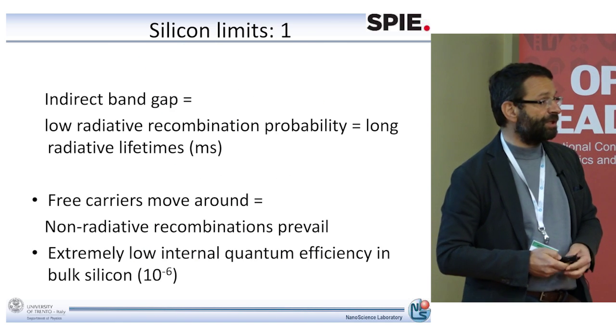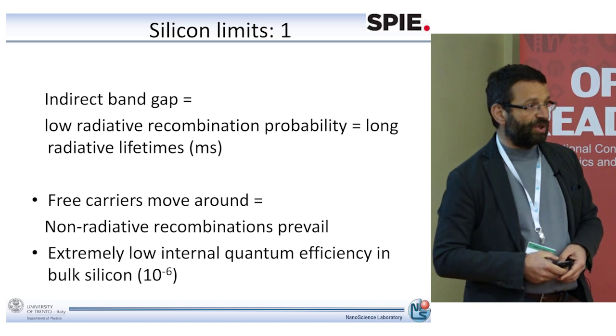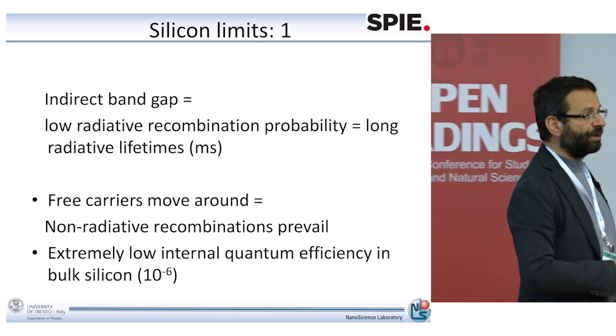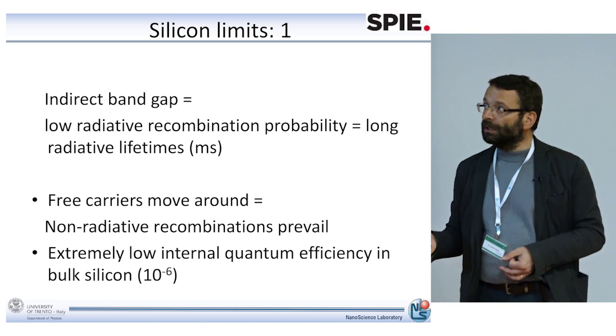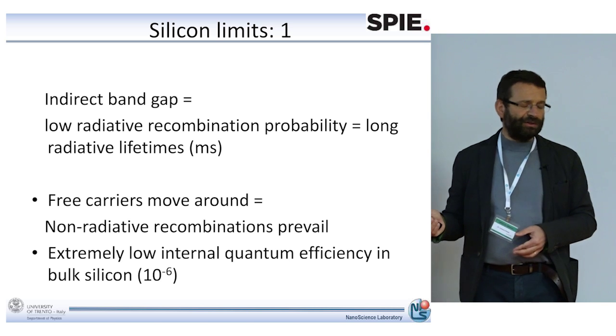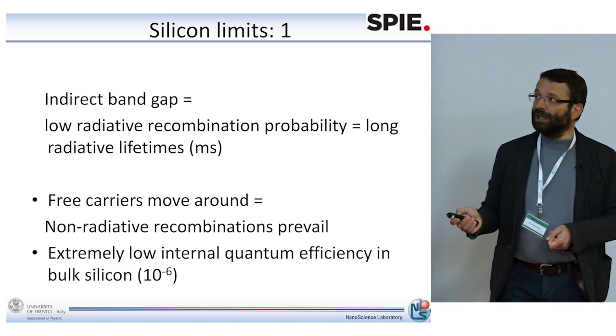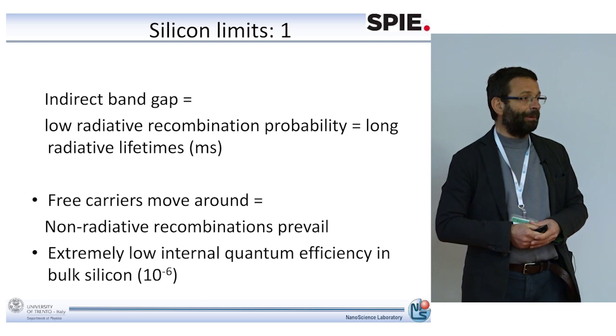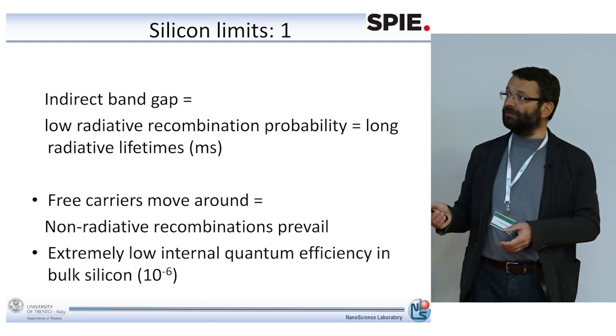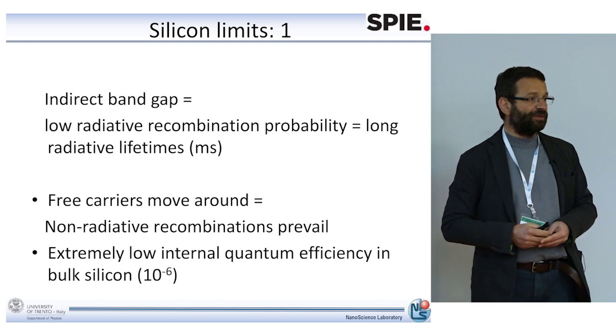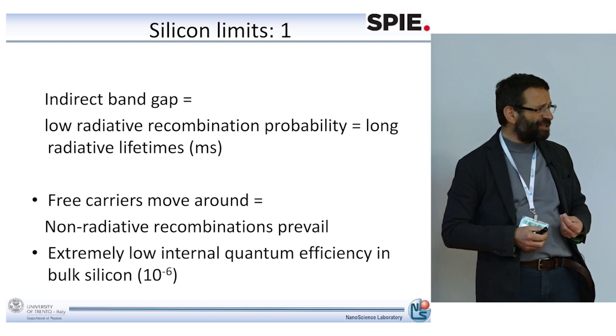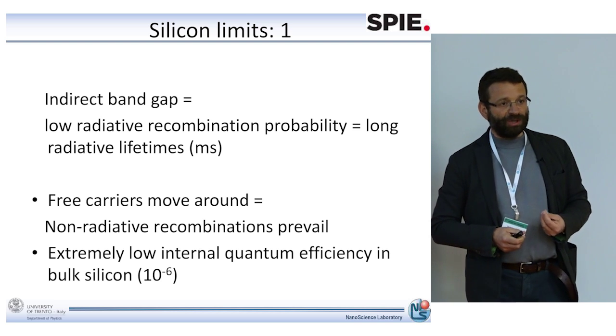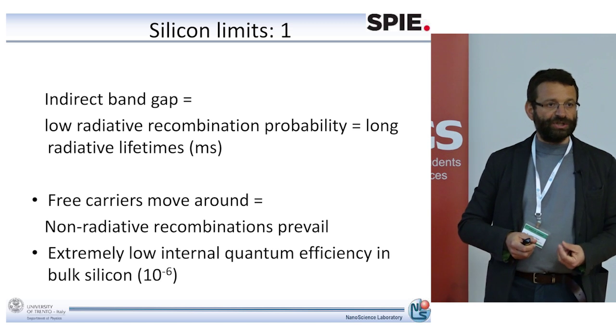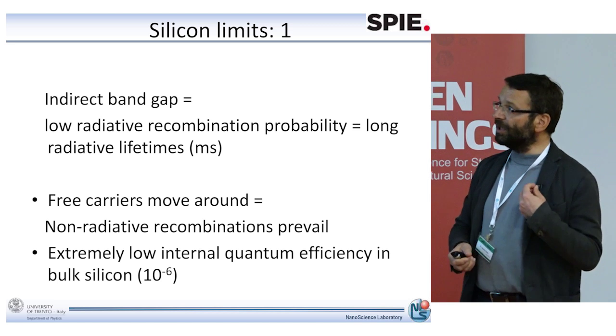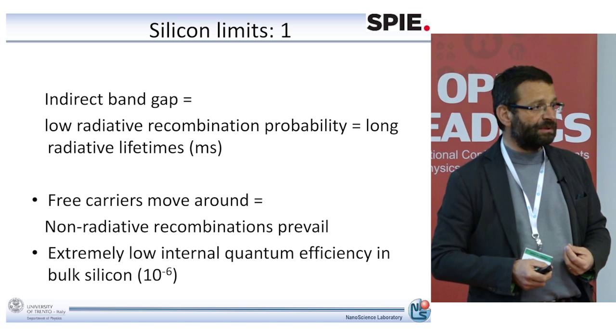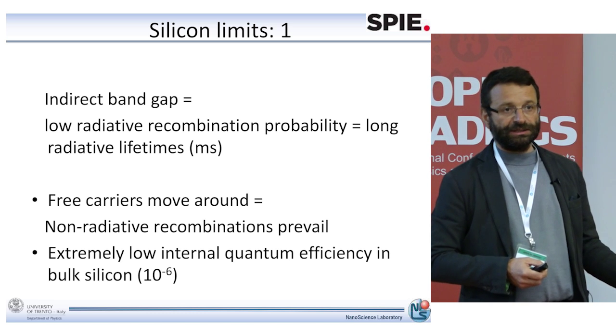So this is a big issue here. Because if we have an indirect band gap semiconductor, it means that the electron-hole pair have a very low radiative recombination probability. So that means that they have a very long radiative lifetime. But actually, this is not a true problem, because we have systems which are characterized by very long radiative lifetimes with which we can make a laser.